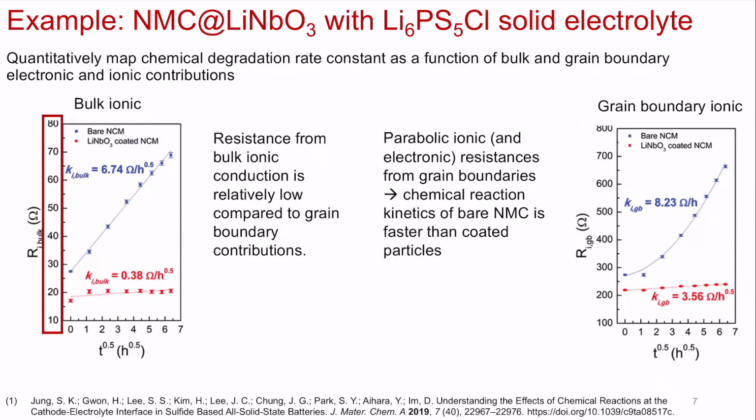This will basically be capped, more or less. So this is before cycling. Now, this will definitely change and not continue to increase linearly, because as soon as you start cycling, beyond electrochemical instability, you're going to have electrochemically driven instability. And what's going to happen is this model tells you that there are instabilities and that there are decomposition products.